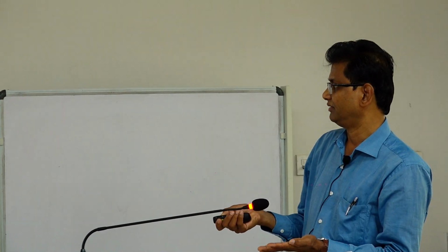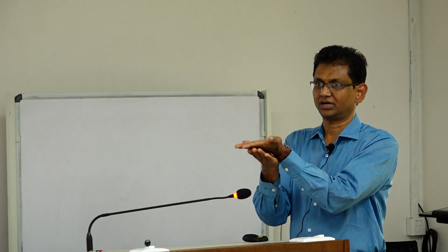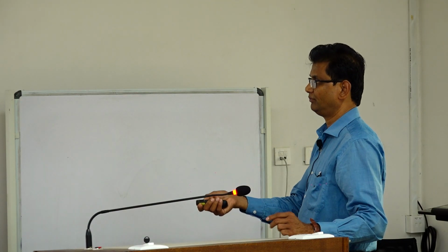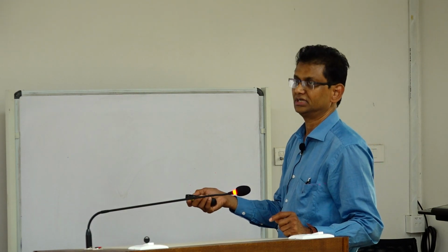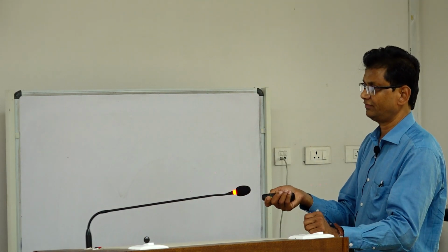Here I said face on gives direct transport to the electrode, and charge transport is inefficient in edge on. Why I said inefficient is, normally if your pi electron is parallel to the surface, the electron will easily transport to the surface, because the pi electron facilitates the charge transport. But if it is arranged vertically like this, where the pi electron is here, the charge transfer may not be efficient. So that's why edge-on arrangement is inefficient for charge transport. This type of information we can get from GIWAXS studies. Okay, the other thing is nanoscale phase separated morphology.